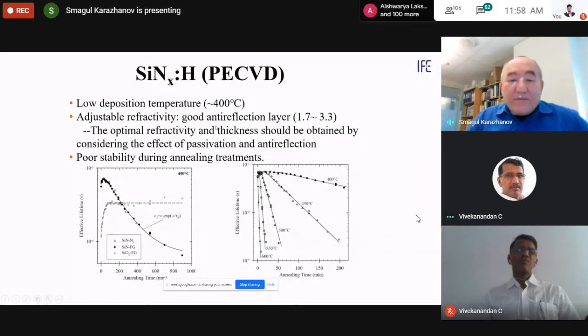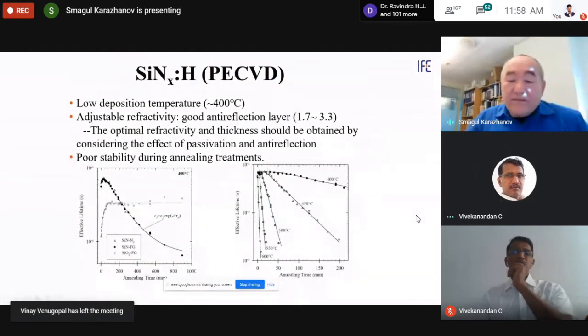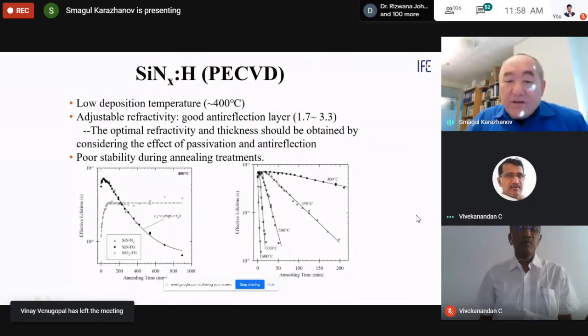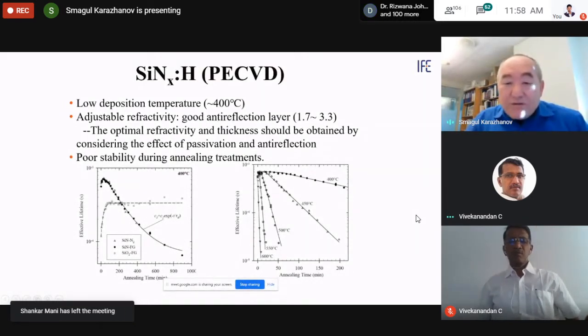One should be very careful about deposition temperature, annealing temperature, and annealing time. In this picture, as you see, the duration of the annealing and the temperature should be really well correlated. For example, if annealing is done at about 500 degrees C, then the annealing time shouldn't exceed just several tens of minutes. Otherwise, lifetime will go down. Effective surface lifetime will go down. So to avoid it, to have maximum lifetime, one should keep a certain duration of annealing and a certain temperature.